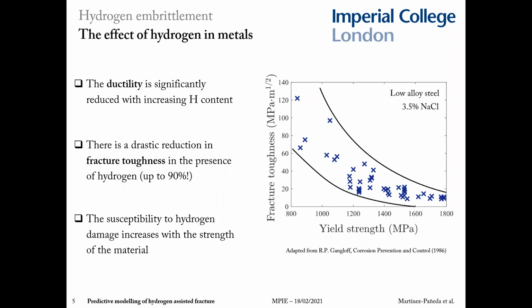You can see here a plot of fracture toughness versus material strength. This is for a given hydrogen concentration, typical of exposure to seawater. And you can see that high strength steels yield a fracture toughness that is below 10 megapascals square root meter, almost like a ceramic. And this figure has two important implications.